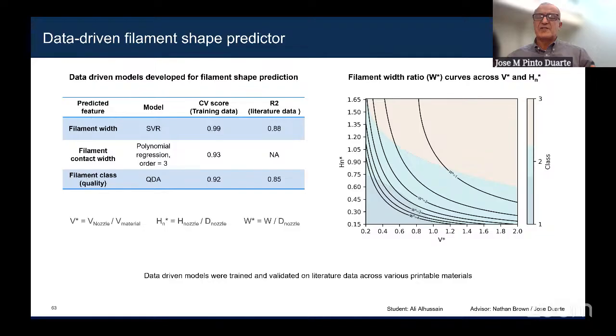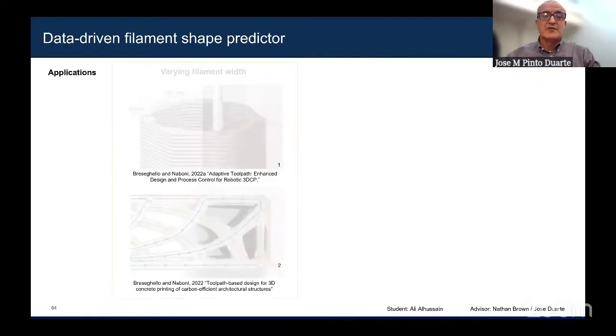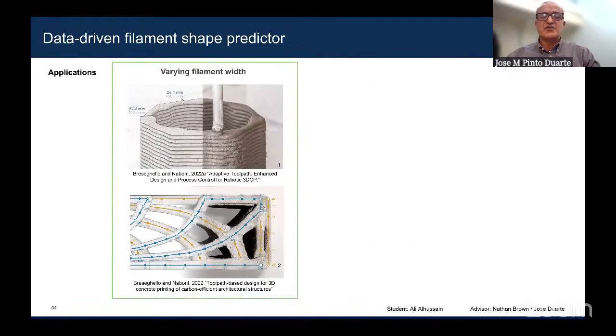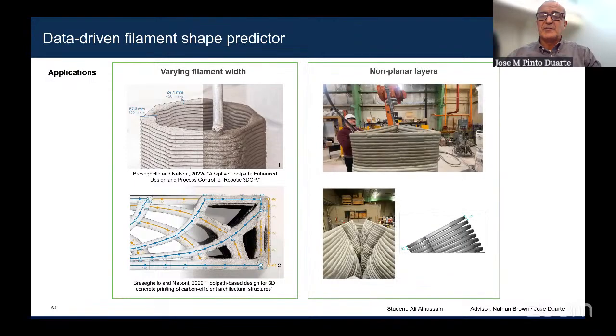And then we can use this system to adjust the printing settings before printing, or actually in real time as well. So this allows us to print filaments with varying width, like you see in this case, but also with varying height. So in this case, you see a structure where we used radial slicing, and so the layer has a varying height, and we use this algorithm to control the printing process to get the layers with that type of shape.